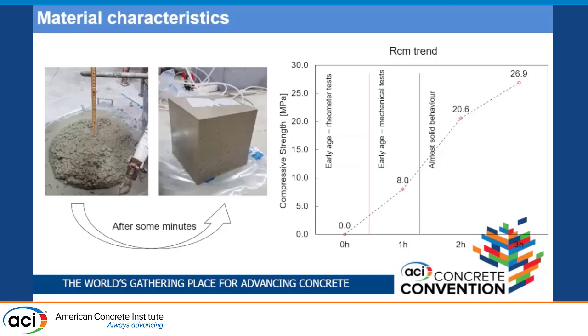From 30 minutes up to 1 hour and a half, the material is no longer in its fluid state, even if it's still plastic, and it is developing strength. In fact, after 1 hour, it has already 8 megapascal of compressive strength, and after 1 hour and a half, it's almost in its solid behavior. So mechanical tests are the best way to test this material.